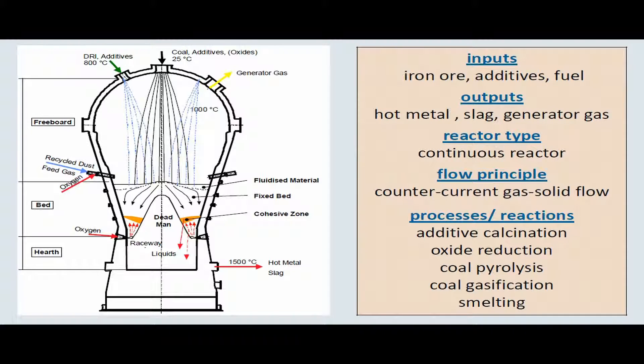The smelting of the direct reduced iron takes place at the lower part of the reactor at temperatures of about 1500 to 1800 degrees Celsius. The gasification and partial combustion of the coal takes place at the upper part of the reactor at temperatures of about 1000 to 1200 degrees Celsius.